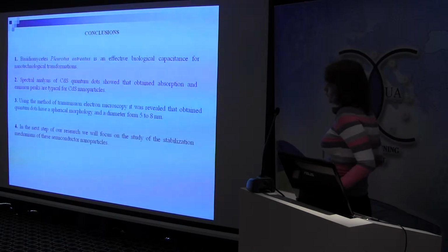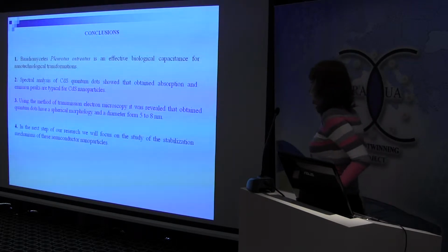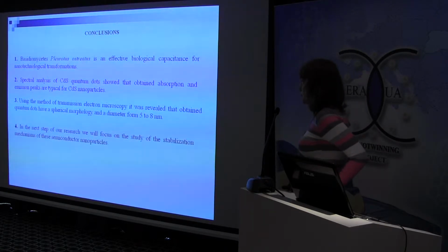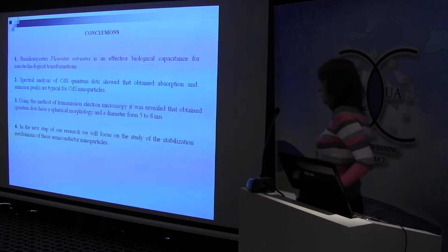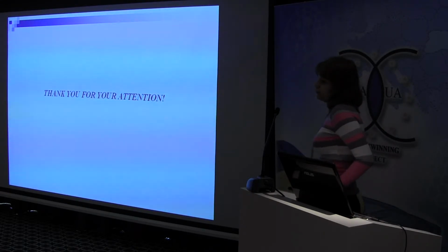Conclusions. The basidiomycete Pleurotus ostreatus is an effective biological agent for nanotechnological transformations. A spectral analysis of cadmium sulfide quantum dots shows that the obtained absorption and emission peaks are typical for cadmium sulfide nanoparticles. Using transmission electron microscopy, it was revealed that the obtained quantum dots have spherical morphology and a diameter from 5 to 8 nanometers. In the next step of our research, we will focus on the study of the stabilization mechanisms of these semiconductor nanoparticles. Thank you for your attention.